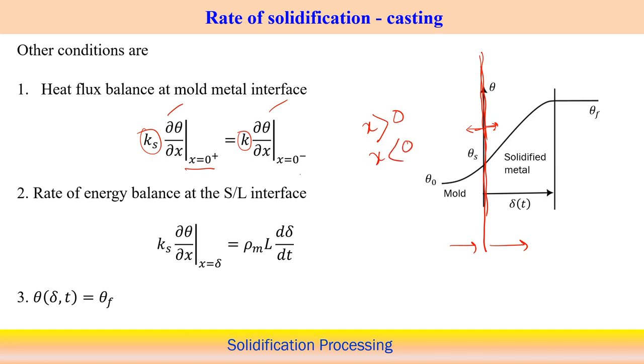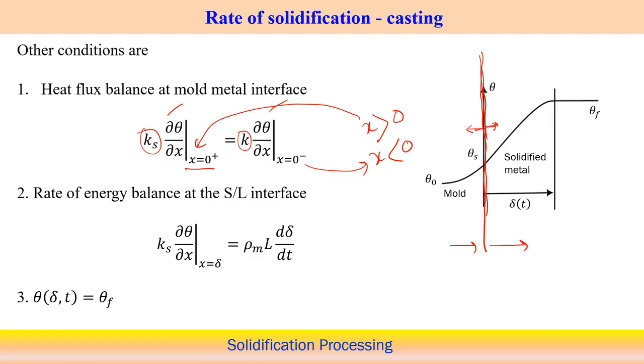So, that means this is for x less than 0, x minus, and x greater than 0 in these cases. In both cases we can calculate del theta by del x, putting in the appropriate expression, and we can clearly distinguish which zone represents the mold material and which the cast material. Based on that, we select the properties, put in these boundary conditions, and from there we can reach some kind of relation. So, this is one heat balance at the mold metal interface that should definitely be maintained.